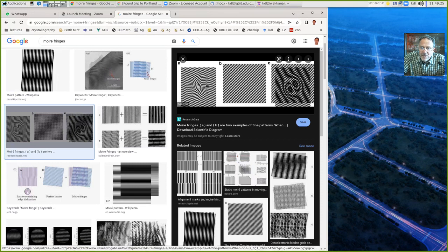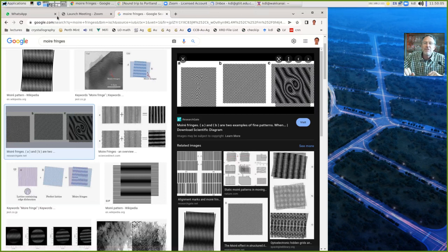And you see there's some distortion, and the distortion field makes up these black and white areas depending on how these lattices superimpose. Whether a dark line superimposes a dark line, then you see the white in between, or if the dark is on the white, then it looks all dark in print here. And very similar, you see that also in crystal lattices, where you have a crystal lattice which is undistorted, and then you have that crystal lattice of this dislocation, just locally around the dislocation.